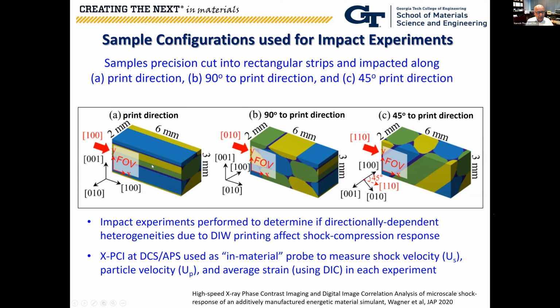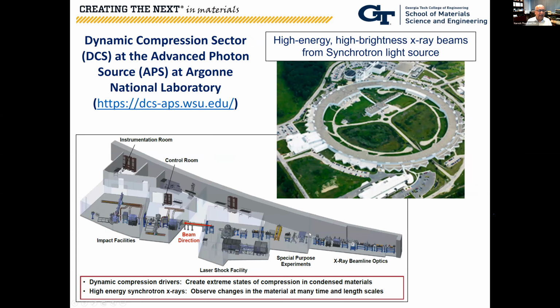The whole idea is to generate images and go inside the material to observe the propagating front, and monitor the speed at which the front is propagating—the shock velocity—and the speed at which the particles are in motion—the particle velocity—and also capture the local strain using DIC analysis.